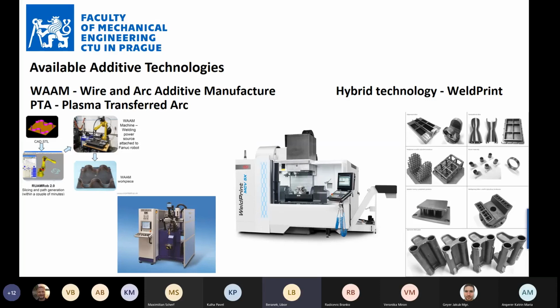Then colleagues here from the university developed a hybrid technology which is called Weld Print, and this is basically an integration of this wire and arc additive manufacturing into the 5-axis milling center. So in one step they can weld a part, and the productivity is like 6 kilograms per hour. So this is quite a big deposition rate for 3D printing. So you can place a lot of material and you can machine it into the final specifications within one technology. So this is called a hybrid technology because it provides additive manufacturing and subtractive manufacturing.